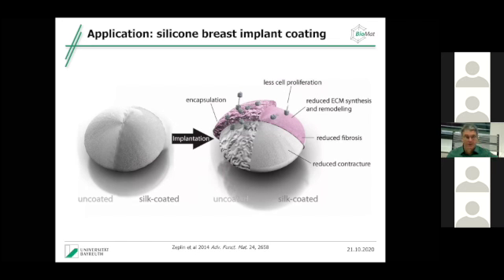So we have a long list, this is very, very positive, because this led us to the model, which was now confirmed in human beings, that if you have a silk coating, and this is here just done to make it much clearer, because obviously we will coat the entire implant for the real stuff. But here we just coated half of the implant to show you the differences, what happens on the surface. On the silk surface, we have no cell proliferation, reduced extracellular matrix synthesis, no fibrosis, reduced contracture. So this looks much nicer than the other part. And this nicer surface, of course, has the benefit that we have less severe side effects. We don't see any fibrosis, for instance, in the patients.